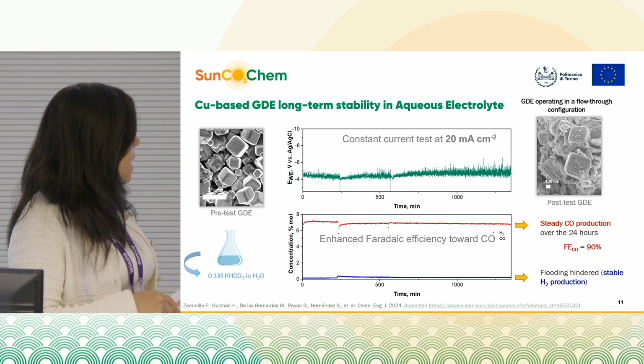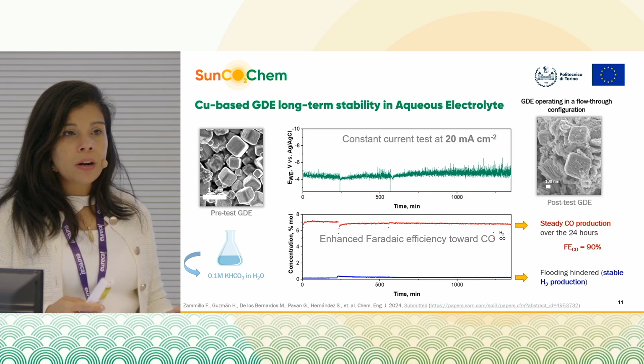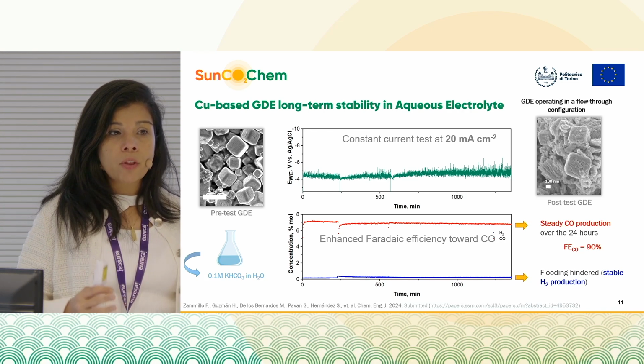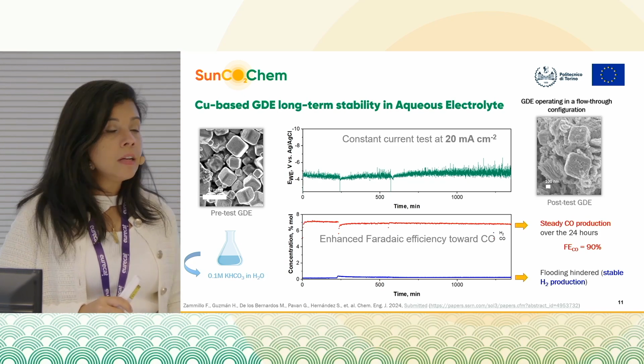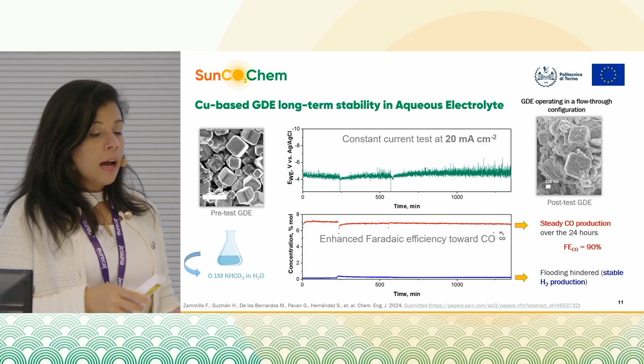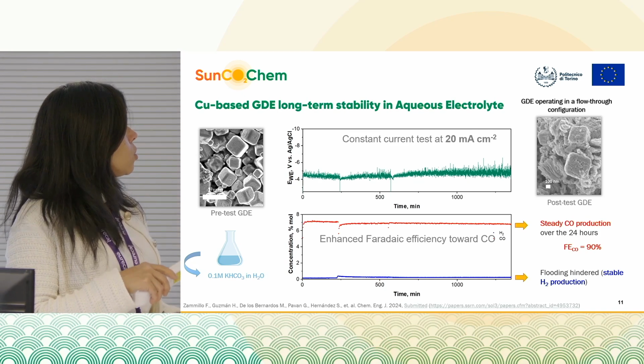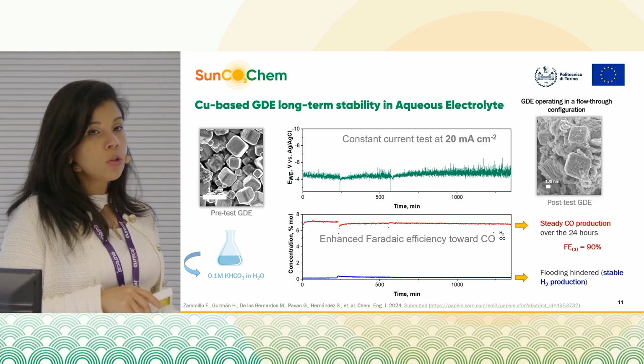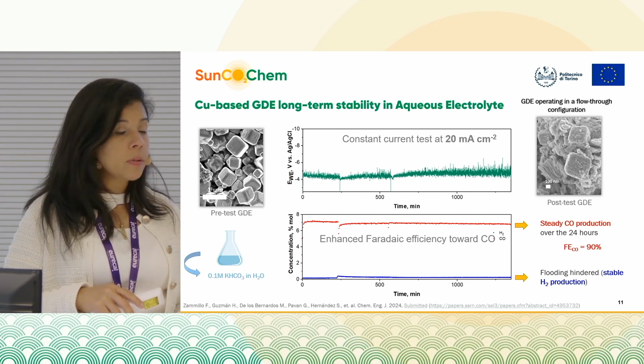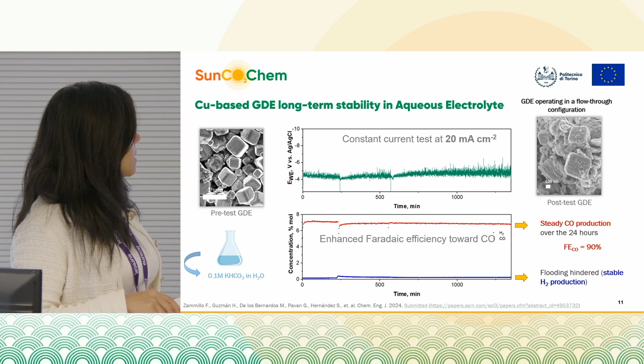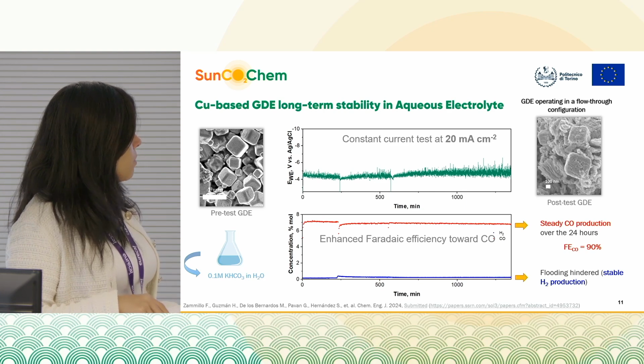So we were able actually to demonstrate that our catalyst was very stable for the production of carbon monoxide and was very selective even at the target condition of our project, that was operating at 20 milliamp per square centimeter. This is a test that we performed for 24 hours in the lab.